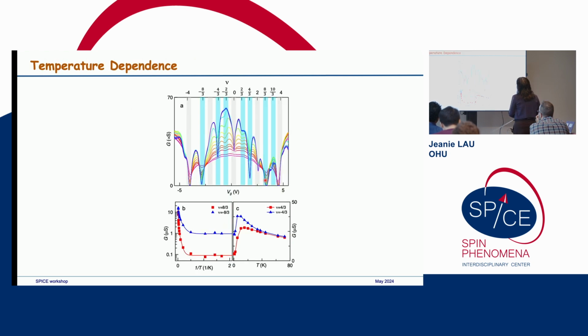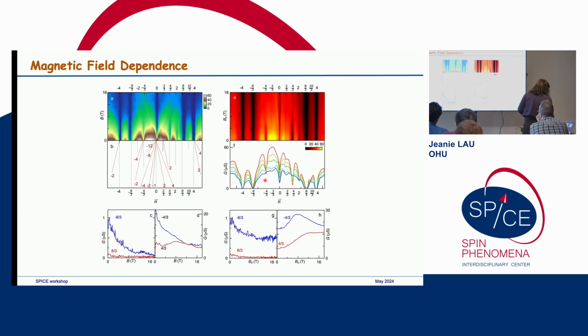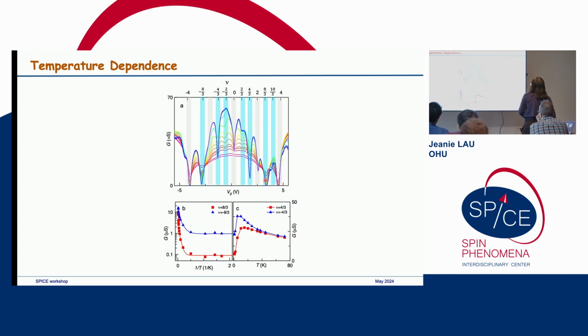Now we can look at the temperature dependence. The 8/3 state is really pretty insulating, and you can fit this to a thermal activation model. This has a gap of about 20 milli-electron volts, and then the 4/3 state actually has a non-monotonic dependence on temperature.